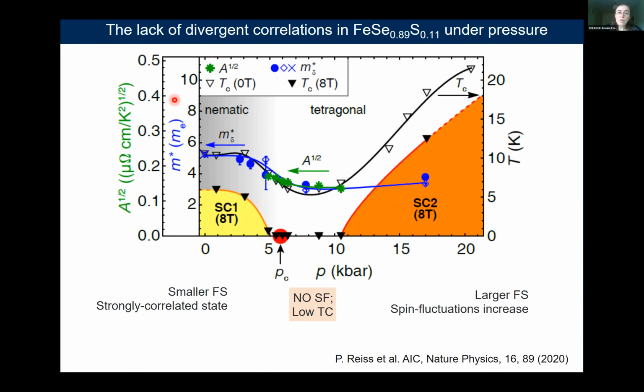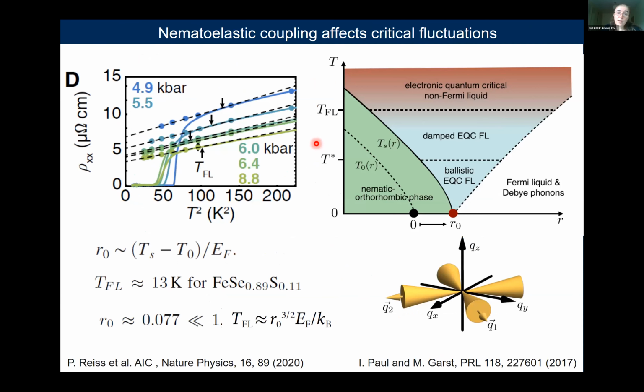And this also occurs under pressure. Similarly, we follow very carefully what really happens to the nematic endpoint, and the changes are very subtle, very small variation in the effective masses and the coefficient from the transport. So there's no divergence. The masses are heavier inside the nematic phase and they decrease outside. So the nematic phase is a correlated electronic phase and no divergent electronic correlations are found at the nematic endpoint. And we suggested that this potentially could be a manifestation of the quenching of the critical fluctuation along certain directions because of the finite coupling between the electronic system and the lattice.